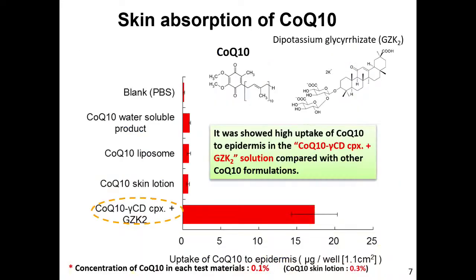So therefore gamma cyclodextrin can make it highly soluble. This is the uptake of coenzyme Q10 to the epidermis, the skin, some kind of cell of the skin. So the absorption rate is very, very high because the micelle size is below 100 nanometer.